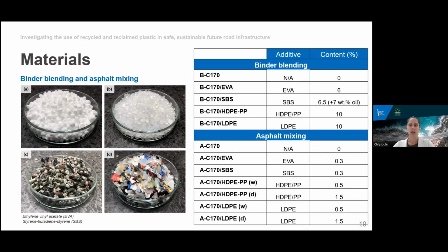asphalt mixing. We do recognize that a third method is discussed when describing the addition of plastics, and that's referred to as the hybrid or mixed method. This method is similar to the dry method, with the difference being that the polymers added are expected to melt or soften during processing. In addition, the added plastics in this research did not replace any of the aggregate portion in the asphalt mix. So in total, we assessed 5 materials during blending and 7 during asphalt mixing.